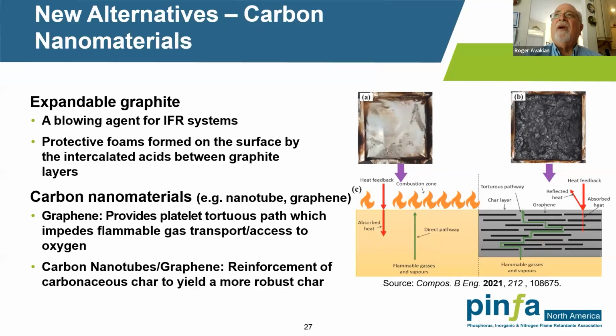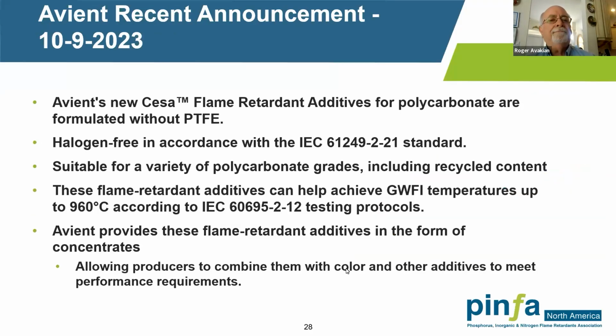I've already alluded to it many times as the integrity of the char with regard to providing a very good barrier, not having pinholes and things like that, so that these pinholes would allow oxygen to ingress, as well as allowing degradation products to basically go out and catch on fire. So basically, the robustness and the integrity of the char is very key in a lot of these systems, and depending on the test. Next slide.